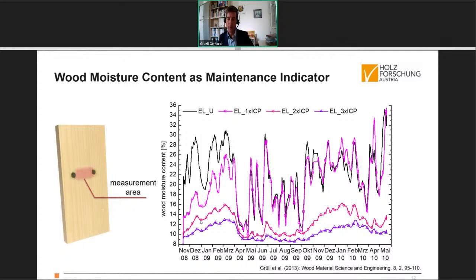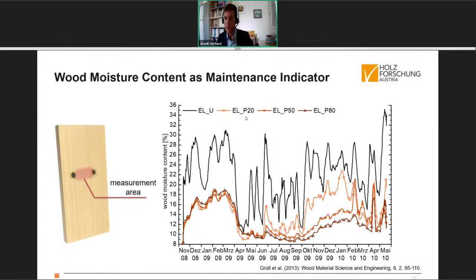With coatings in general, with intact coatings, these fluctuations are much smaller because of the moisture protection of the coating. And with 3 times ICP, it retained very nicely in a low area of wood moisture content with very low fluctuations. But with 1 time ICP, you see the fluctuations start moving very much during the first half year of exposure, and it comes to the same fluctuations in wood moisture content as uncoated wood from this point in time. So that means here the coating is completely degraded, has no moisture protective function anymore. The next example is a water-based system, again in 3 different dry film thicknesses.